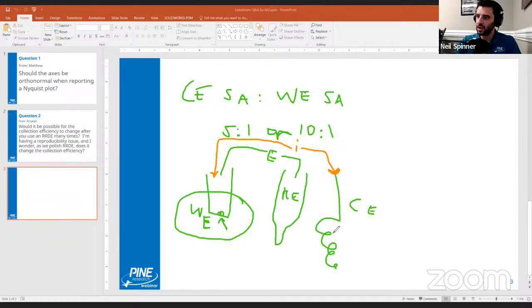Whereas if it's the other way around, if the counter electrode has a small surface area, it will have to work harder. Basically, the potentiostat will have to work harder to provide the current that is required at the working electrode. And if that's the case, the potentiostat is going to have to increase the voltage a lot. It's going to potentially lead to problems in your solution, unwanted side products. So basically, the counter electrode just needs to be something that's very conductive, relatively inert, and something that can have a high enough surface area.